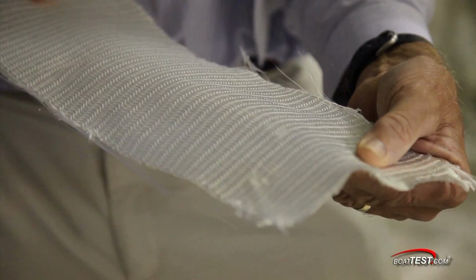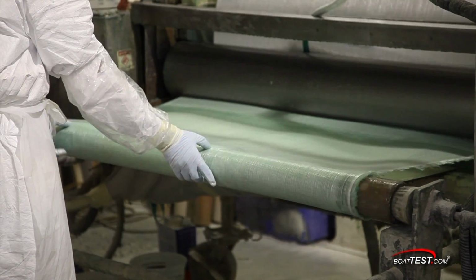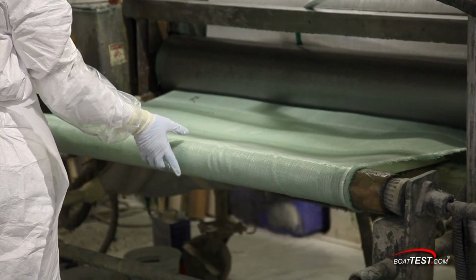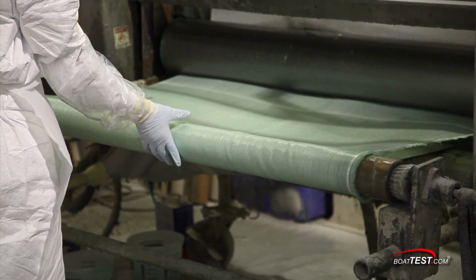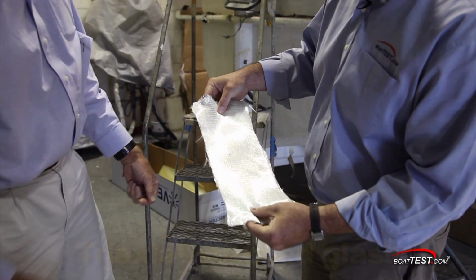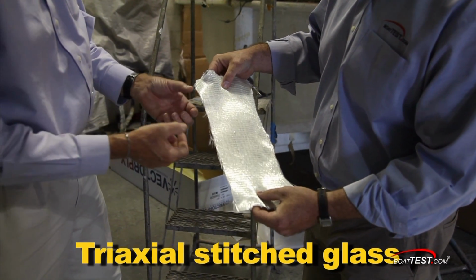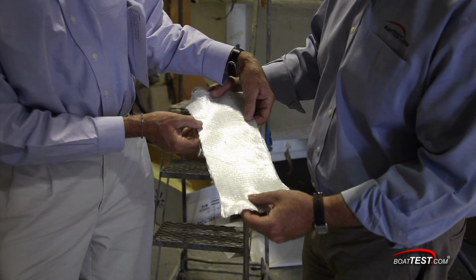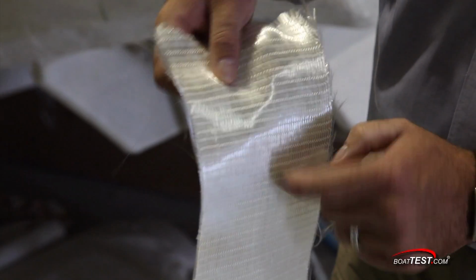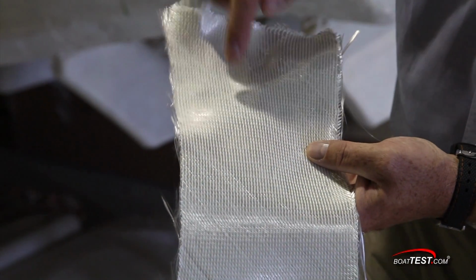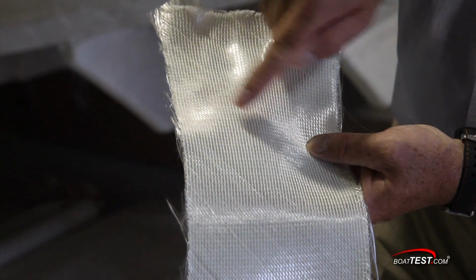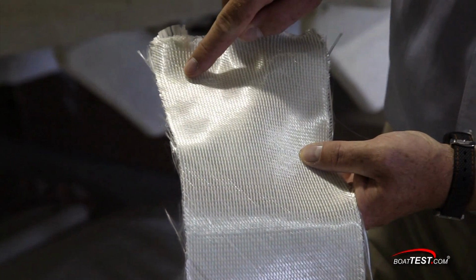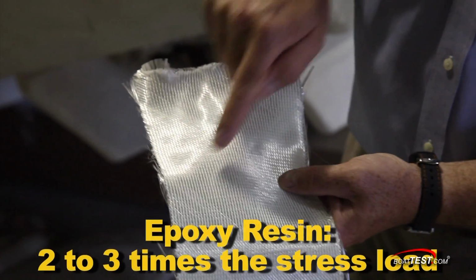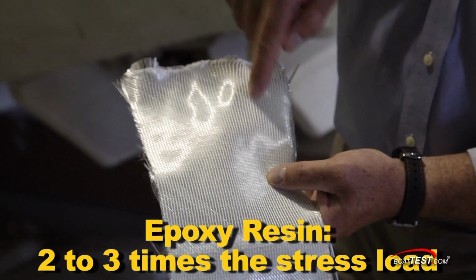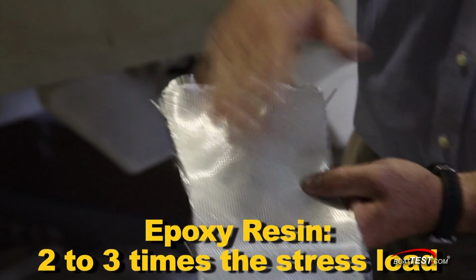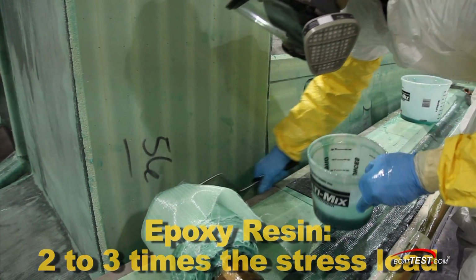On top of the tie coat, they apply an epoxy laminate of multiple layers of unidirectional fiberglass specifically oriented with the loads in the structure of the boat. This sample of triaxial glass shows the longitudinal fibers that run the full length of the vessel, and on the other side, run at plus and minus 45 degrees to take crosswise loads. MJMs are built with epoxy resin because of its exceptional toughness, which allows it to absorb strains up to 2 to 3 times what normal polyester resin can withstand.